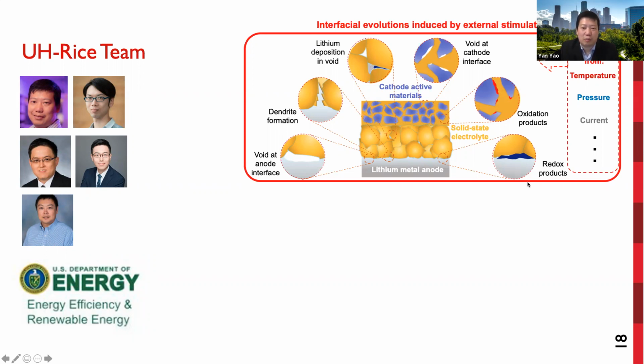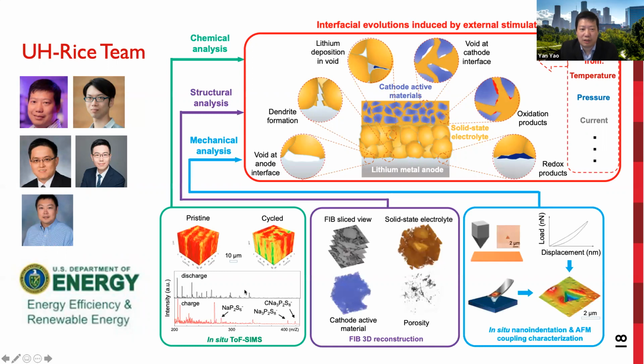So we decided to approach this complex origin of battery failure using not only one technique, but a combination of three techniques as a tool set, including time-of-flight SIMS measurement for chemical analysis. We will use FIB 3D reconstruction inside the SEM for structural analysis. We are also using in-SEM nanoindentation for mechanical analysis.